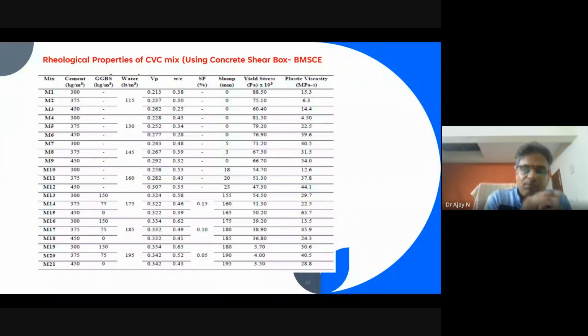Here we check the rheological properties after placement of the concrete in the formwork. The rheometer considers the pumping effect when the concrete is pumped, but we check when the concrete is at rest, after the pumping effect and vibration are done and it has settled in the formwork. So we are checking something more relevant to field conditions. We are checking the yield stress and viscosity. The rheometer checks at the beginning, after pumping, but we are checking more relevant to the field application point of view.